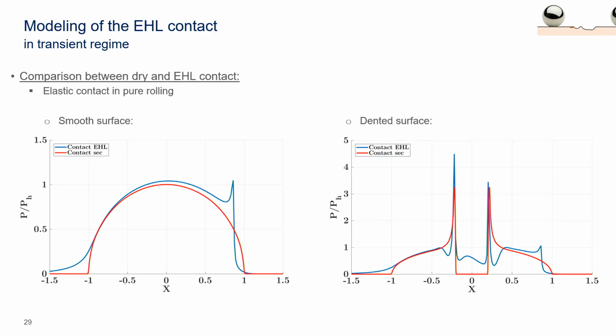Just to make a comparison between the dry contact and the lubricated contact, in red you have the Hertz solution, again as we have seen Monday. Okay, this is the EHL solution, and you can do the same for the dry contact with a dent. Then in red you have the dry solution with a dent, and in blue you have the EHL solution. Okay, then you capture what happened around the shoulder. You miss what happened in the convergent. You miss what happened within the oil pocket because you have no pressure, but okay. Also it's a good approximation to use a dry contact model for that.